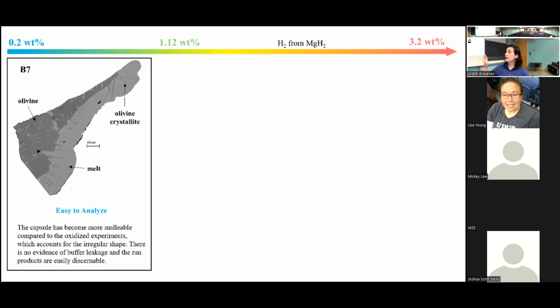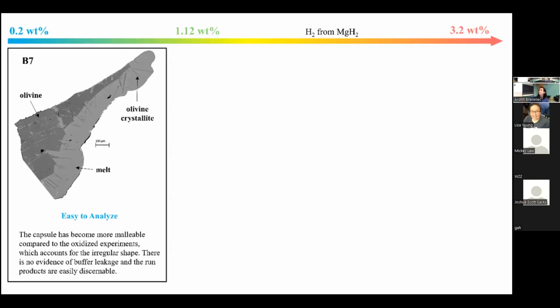And I will note that I didn't add the water as water. That is, I didn't get a syringe and drip it into the sample. What we actually did to get very reducing conditions was thermally decompose magnesium hydride. And so using that more reduced form of hydrogen, we're able to enforce a much, much lower oxygen fugacity. And this worked pretty well for the samples that didn't have a lot of hydrogen in them. You can see that we were able to synthesize very large olivine crystals relative to these kinds of samples and very large melt pockets, which are exactly what you want for analysis.